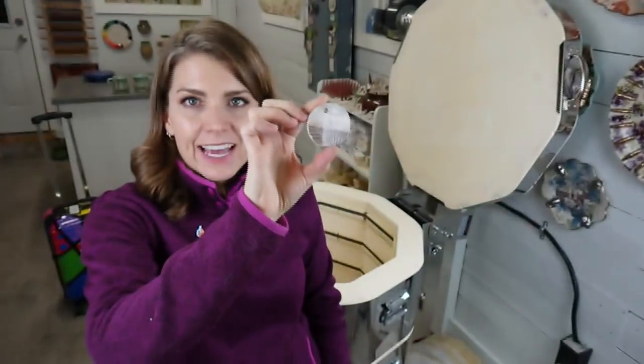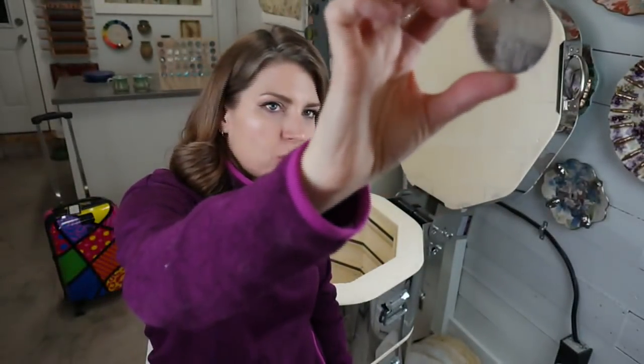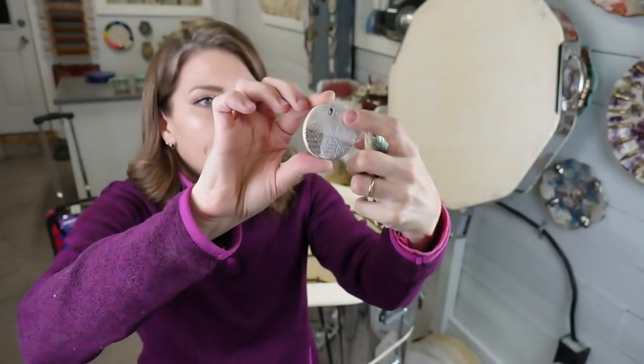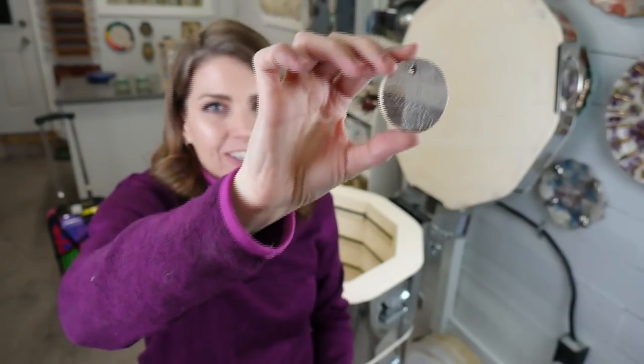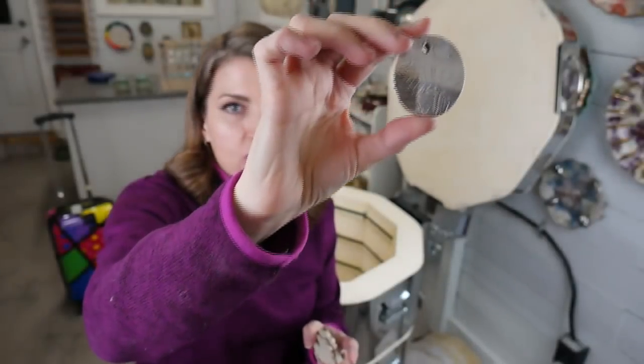Some more ClayShare magnets coming out of the kiln. This is from my making-a-test-tile-board class — the little test tile with tree bark and Perfect White. I have tree bark on the bottom, not wiped back, on the top wiped back, then one coat of Perfect White on one half and two coats on the other half. Not wiped back is really cool, and I think only one coat of Perfect White is all you need — more than that becomes very opaque.